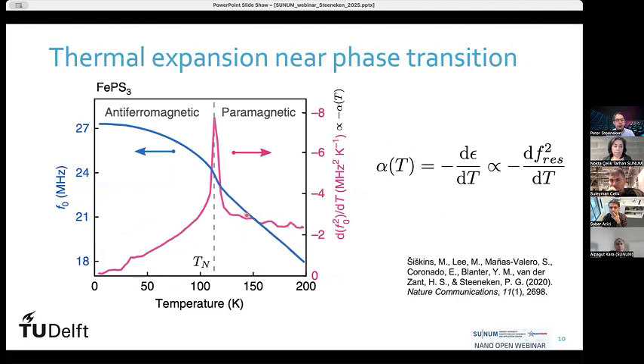So what happens now if we do this calculation? We determine this thermal expansion coefficient, and this gives us this purple line here, and it shows a huge peak close to the temperature of 114 Kelvin, at which this material, our iron phosphorus trisulfide, becomes antiferromagnetic. Above this temperature, the spins are still randomly aligned, but below it, they all become nicely antiparallel organized. And this peak basically tells us that these magnetic excitations are strongly changing at this temperature.